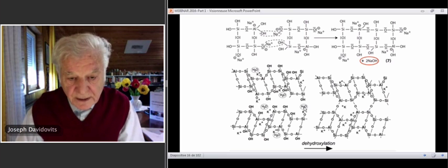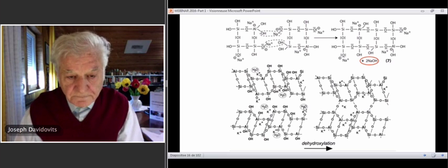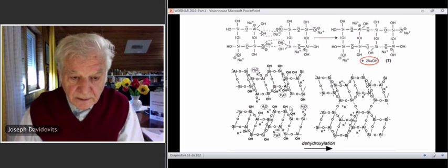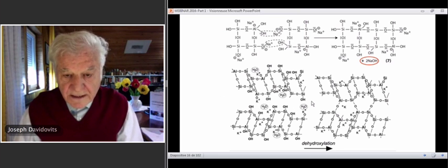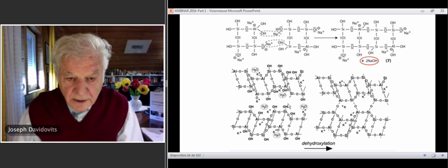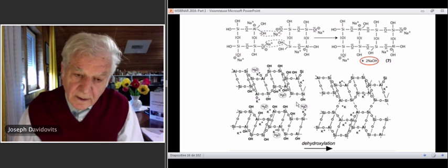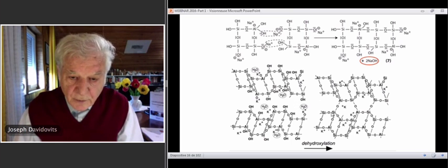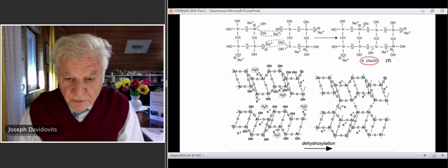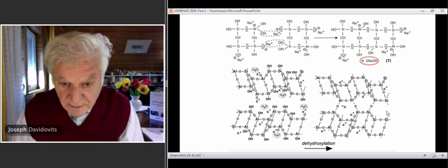At the beginning, we are still in a medium that contains some amount of water, and these molecules, if they are heated at a temperature higher than 250 degrees C, the hydroxylates or the OH are evaporated, and we have the formation of sialate groups between the system, and it turns into a ceramic material.